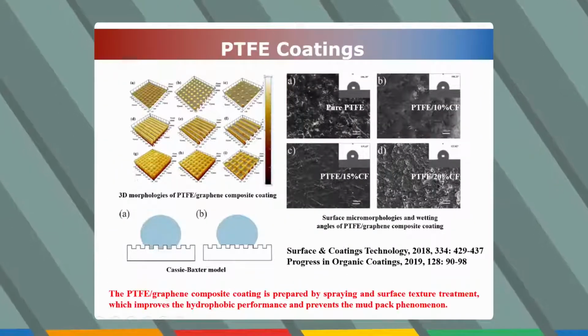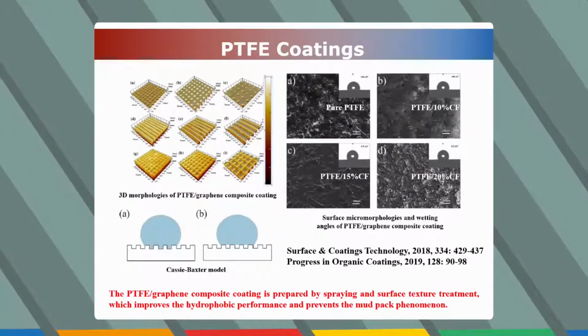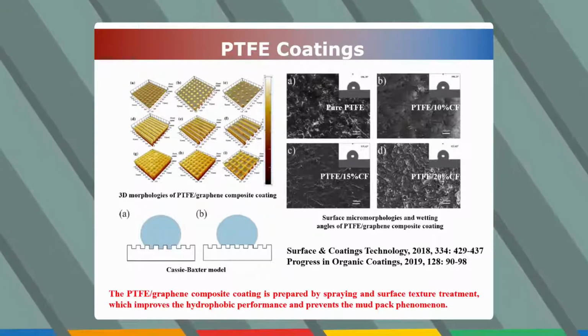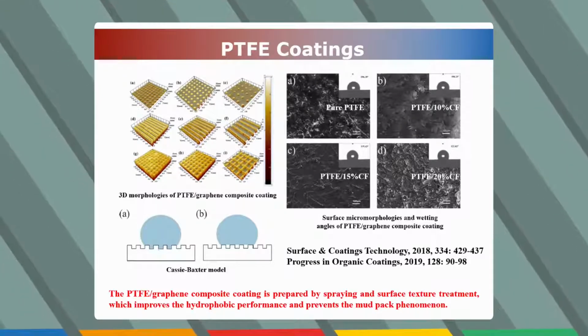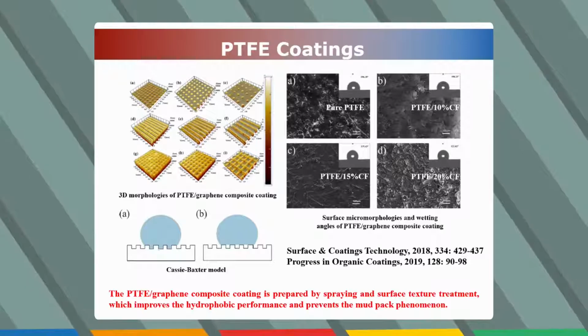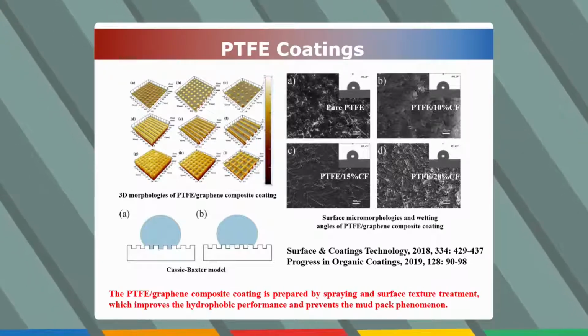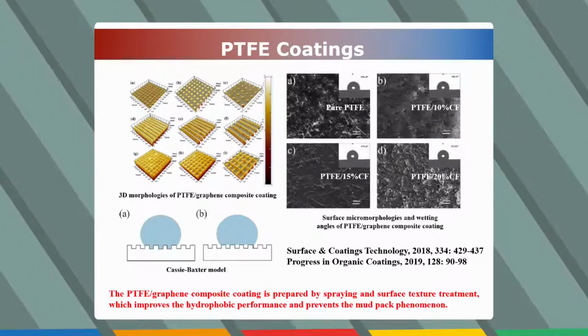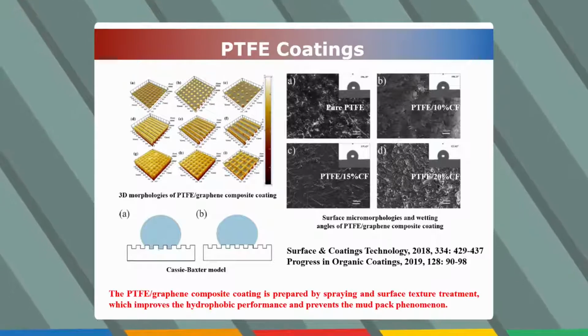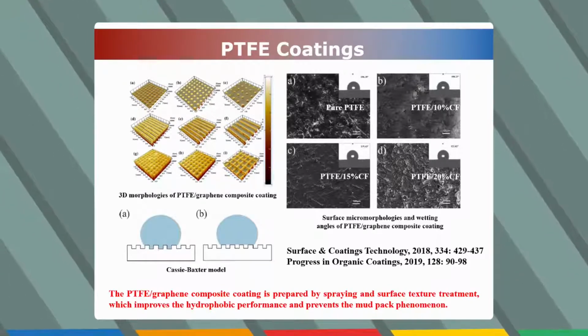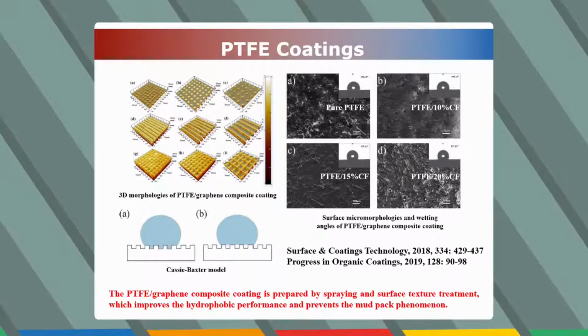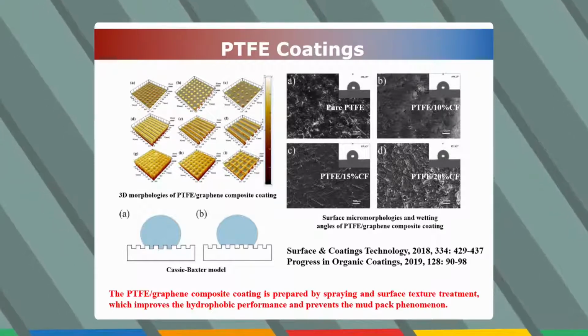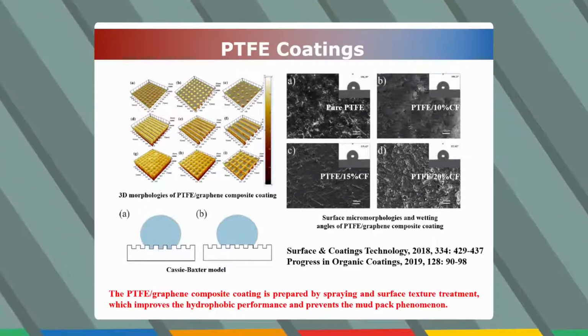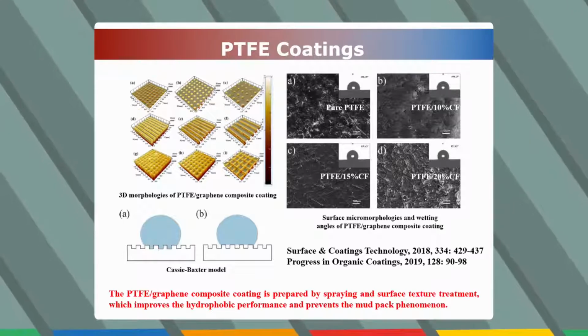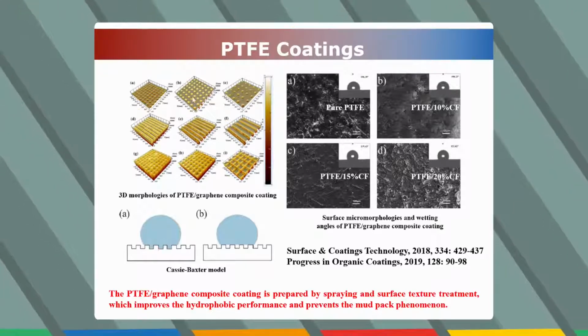This slide shows that PTFE and graphene composite coating is provided by spraying and surface texture treatment technology, which improves the hydrophobic performance of drilling tools, and it can effectively prevent the mud pack phenomenon during the drilling tools operation.